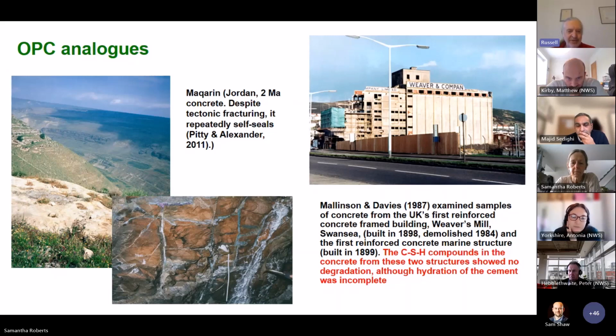For natural systems, one of the best we have and what's best studied is the Maqarin site in Jordan. The shot on the left, I'm standing on the top of the hill in Jordan, and that ridge you see in the distance is actually Syria. So it's right on the Jordanian-Syrian border. And this 2 million year old natural concrete, as you can see in the middle photograph, it repeatedly seals itself. There's some local tectonics going on in that valley, and the concrete fractures.